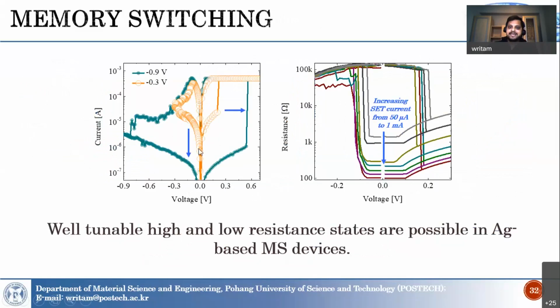Here you see the same structure, the same silver, hafnium oxide, and platinum structure. It can show a nice memory switching behavior without changing any material. In these devices, we can even achieve multiple levels with just proper tuning of the compliance current.